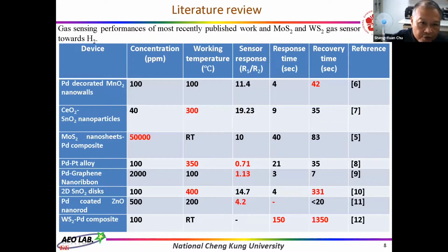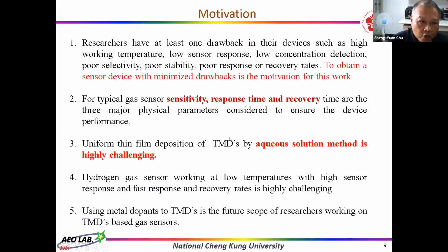However, from the literature review, these references have at least one drawback. For example, in reference 6, the recovery time is too poor, and in reference 7, the working temperature is too high, and in reference 5, the gas sensor detection concentration is too low. So in this motivation, we try to make a sensor device with minimized drawbacks. And also, as I mentioned before, usually the TMD films are synthesized by using the CVD method. And in this work, we try to use the aqueous solution method, which is highly challenging.